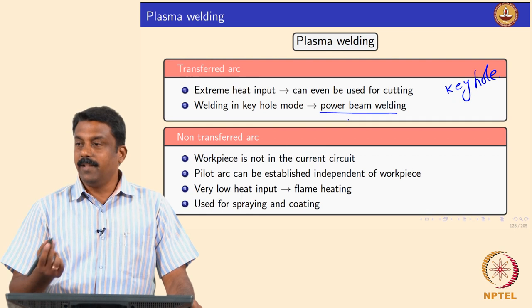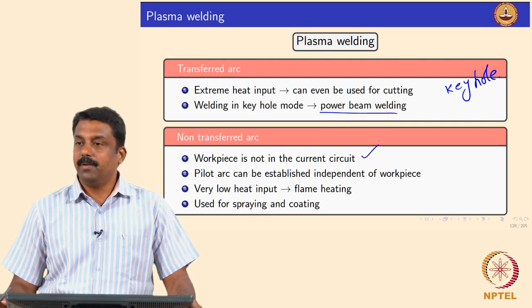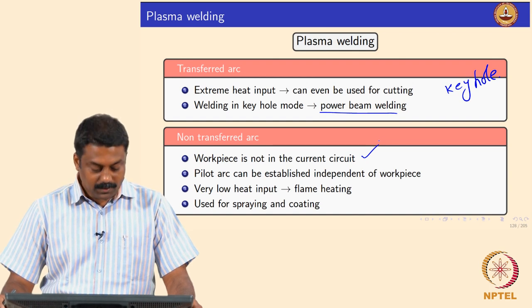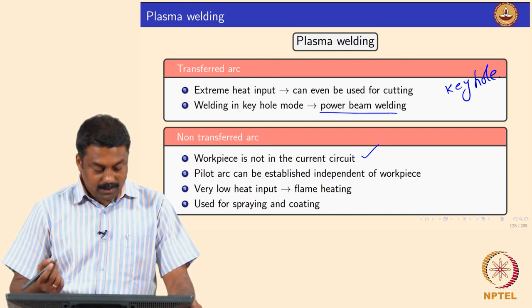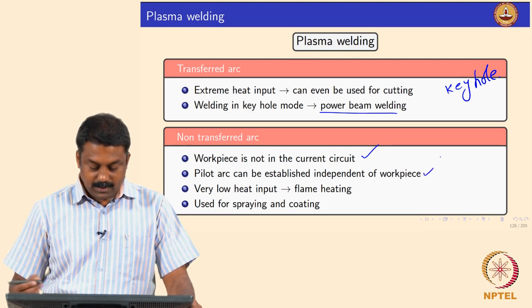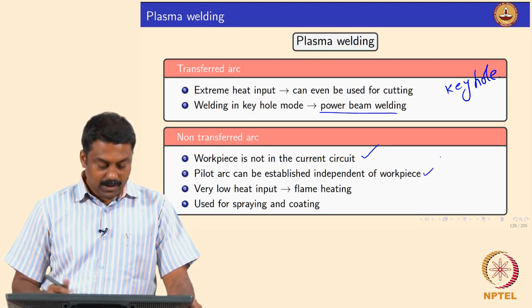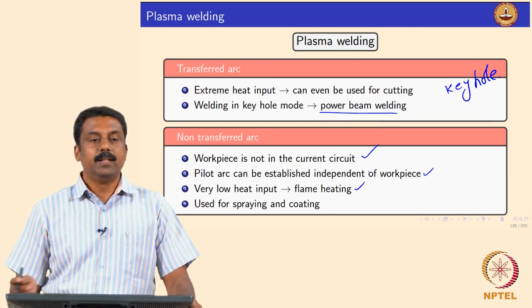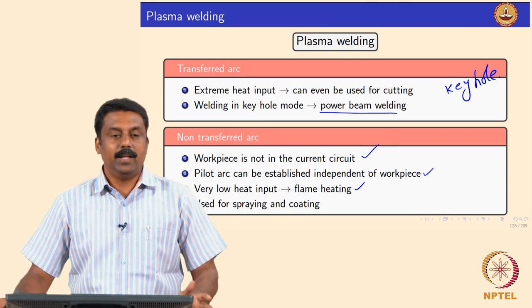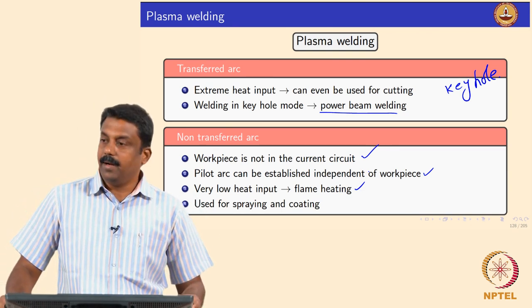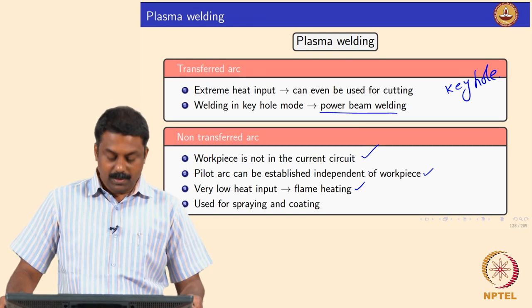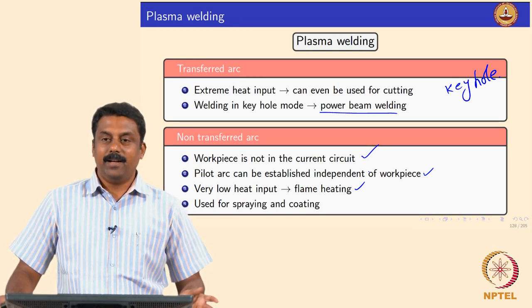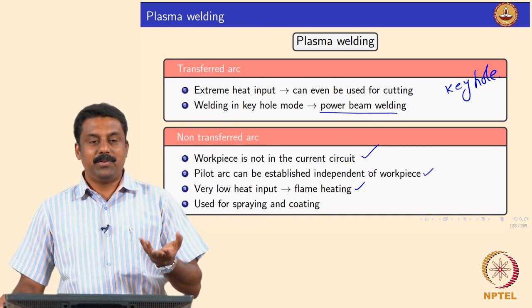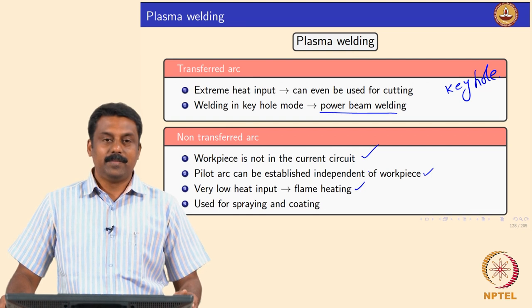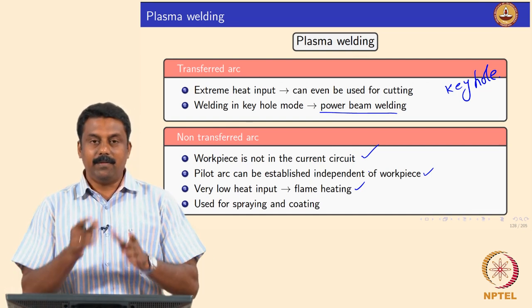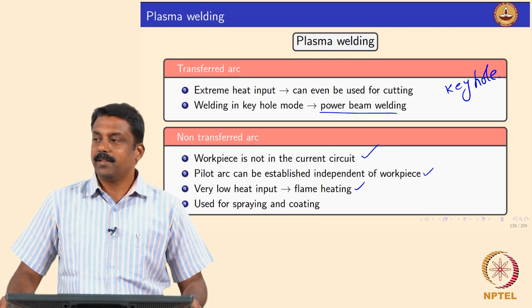And the non-transferred arc is also very handy, because the workpiece is never in the current circuit, isn't it? The arc is struck between the cathode and the copper anode. So it is established independent of the workpiece. And it can be used for heating, spraying and coating. If you want to do cladding powder deposition, you can use a simple powder. And you can modify the conventional GTAW torch into a plasma torch. So very simple. The only thing is you need to have a constricting nozzle attached to that.